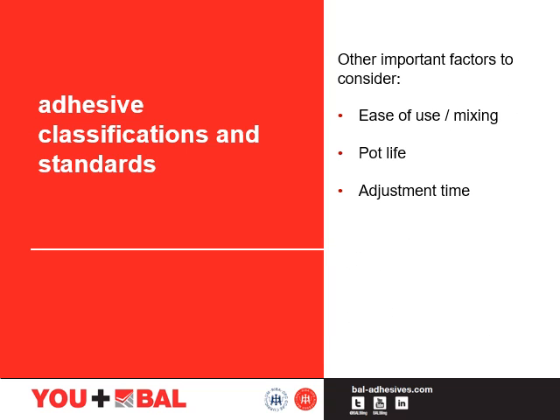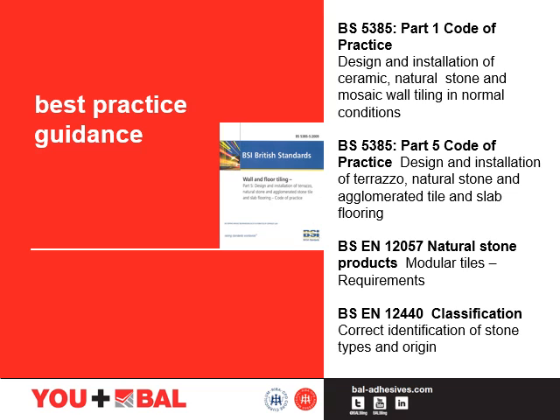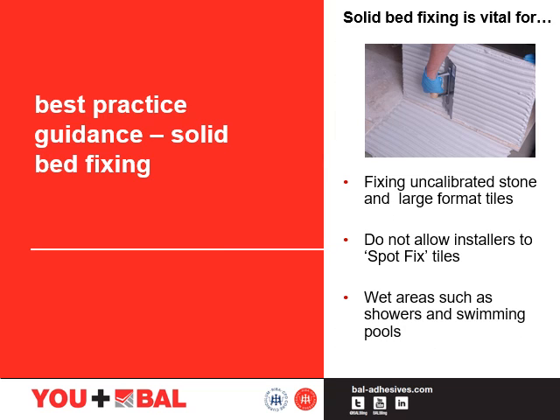The first three adhesive characteristics are not tested for in accordance with EN 12004 requirements, but are important to the end user and assist in providing an adhesive which is easy to mix and apply with a good working time, allowing for adjustment of pre-bonded tiles within a given time. BS EN 12002 has a test and measure for transverse deformation of tile adhesives, giving us S1 which is deformable and S2 which is highly deformable. Best practice guidance can be found within these documents and it's essential for the use of natural stone. When tiling with natural stone, solid bed fixing should be adopted to achieve 100% bonding at the back of the tiles.